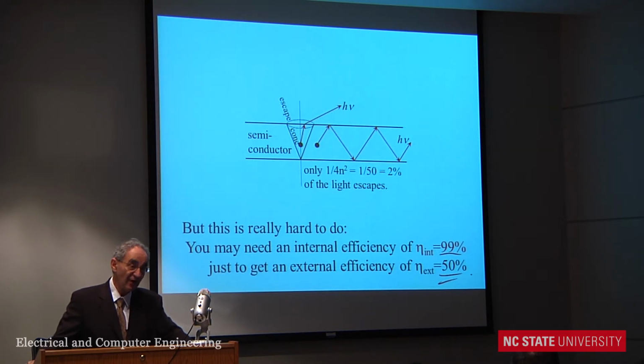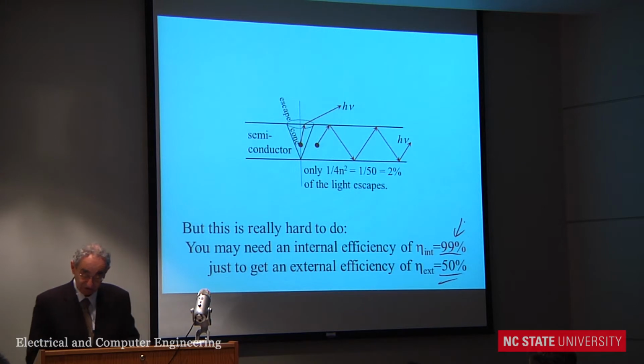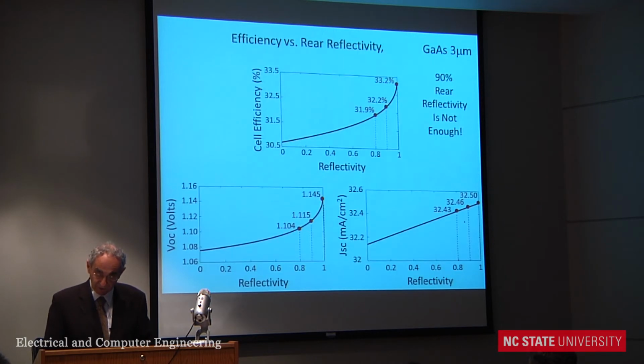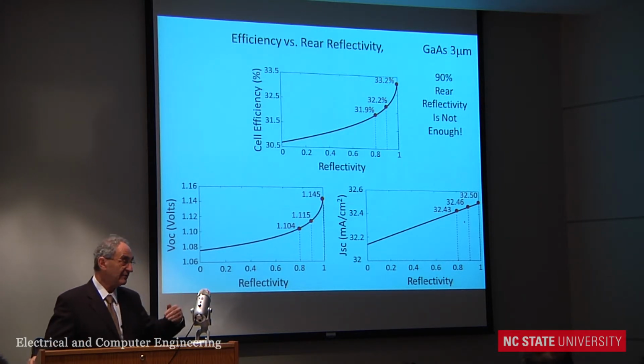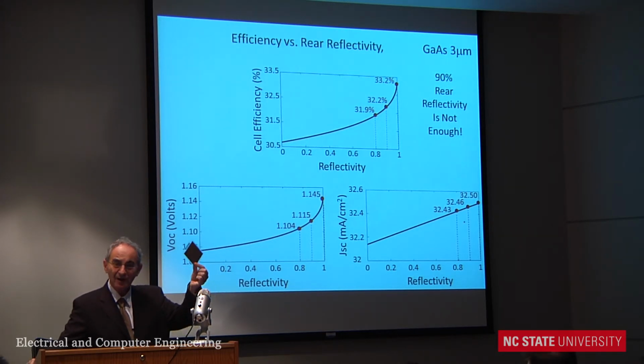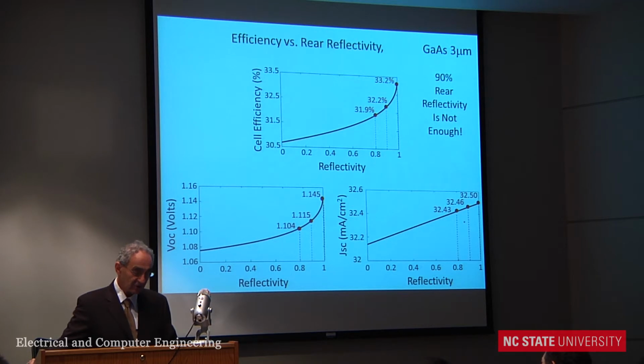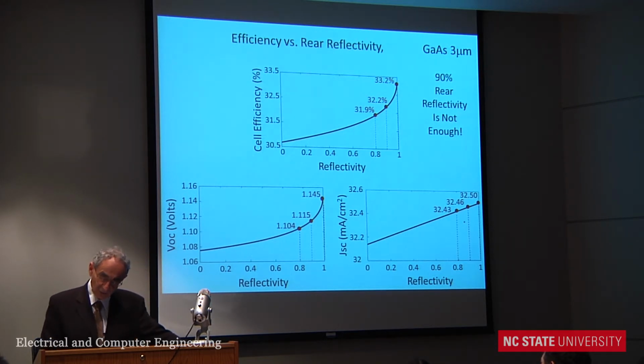However, the 3-5 materials are an amazing gift of nature because they are the most efficient. They will actually give you well over 99% luminescence efficiency at room temperature. So they're quite remarkable. Now what about the reflectivity? Since you're bouncing around internally, you better have a good rear reflector. The ones I'm showing you, you can see, this used to be a company secret, there's copper on the back. And you get quite a good reflectivity. How good does it have to be? Well, 90% is not good enough. In fact, if you look at the efficiency as a function of reflectivity, your best region is above 95%.